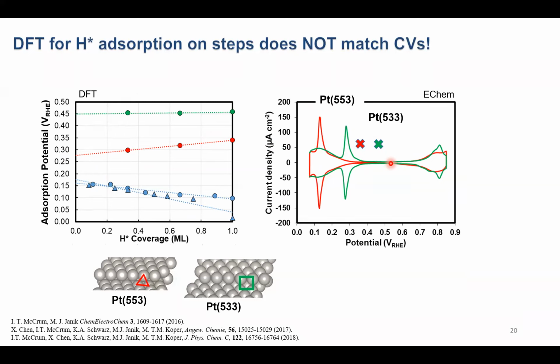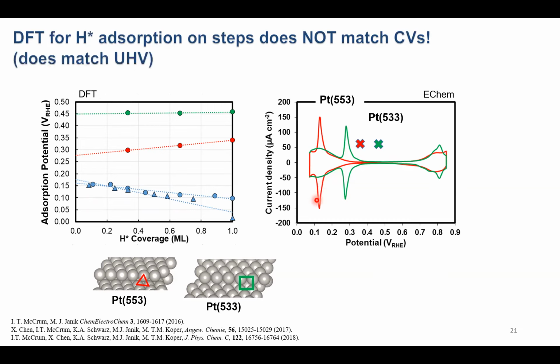We get wrong numbers. But we can do better than that, and we can try to understand why DFT got this wrong. And what's interesting is that if we compare our energetics to the adsorption of hydrogen on stepped platinum in the ultra high vacuum environment, then we do match those thermodynamics. And so I'm not showing that here, but just trust me that we match what's measured in ultra high vacuum. And so that would tell us that it's not really the DFT that's wrong, it's that we're missing something that's going on in the electrochemical environment that's different from ultra high vacuum.